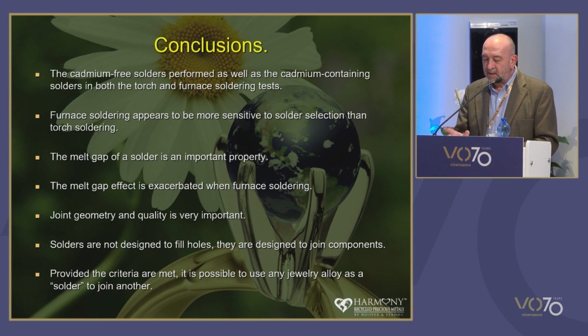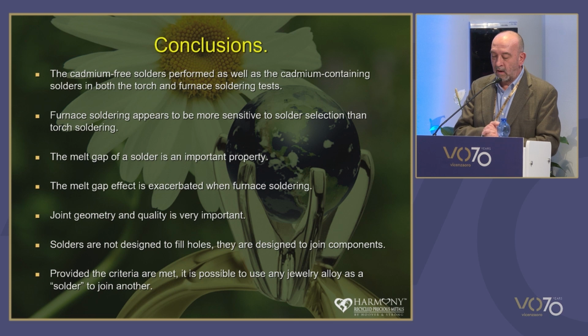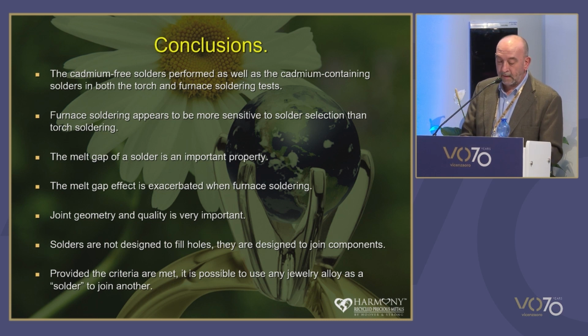Yeah. So it's particularly relevant when we're looking at joint geometry or lack of, as the case may be, and provided the chemical and physical properties of a jewelry alloy meet the criteria for wetting, elemental compatibility, and melt gap is sufficiently narrow, it should be possible for any jewelry alloy to be used to join another one. And our final test demonstrated this.